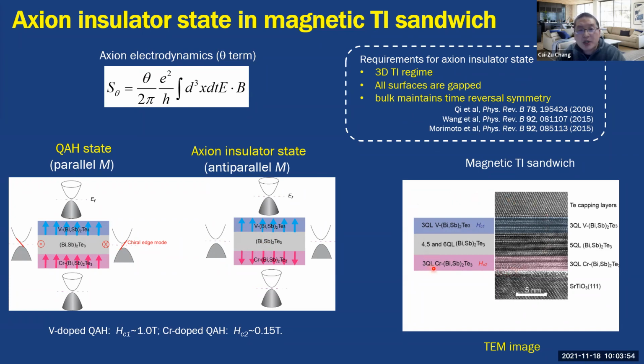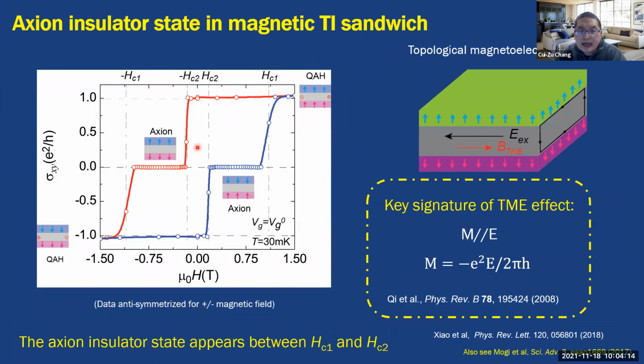So this is the sample we grew in our experiment. We grew 3 quintuple layers of chromium doped TI, and also 3 quintuple layers of vanadium doped TI on the top, and in the middle we varied the thickness. And this is the TEM image of our sample. It shows the pretty good quality of the magnetic TI sandwich structure here. Let's take a look at the transport results.